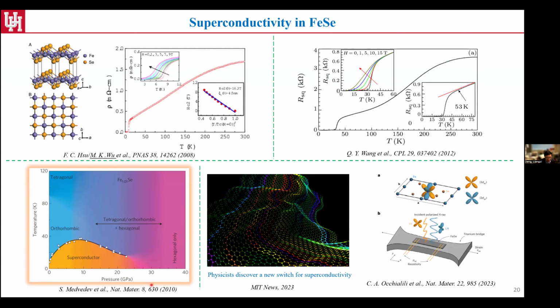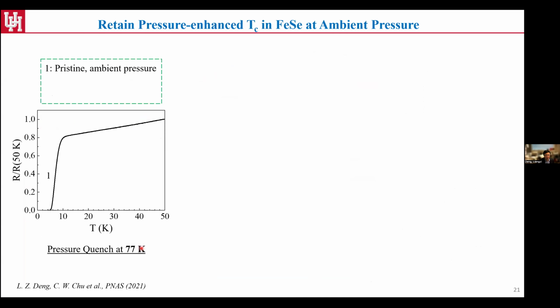So we're focused on these high pressure results here. That was done early by Bob Cava and other colleagues. When they applied pressure, they mapped out the phase transitions, and the TC, as I mentioned, can go up to 40 Kelvin, and it comes with two structural transitions, from orthorhombic to tetragonal, and eventually to hexagonal, and then it loses the superconductivity. Right. So what we do is, first we carefully measure the ambient pressure pristine sample. The onset is around 9 to 10 Kelvin. That's consistent with what everyone observed. And then we add pressure, pushing the onset TC to a little bit above 30 Kelvin.